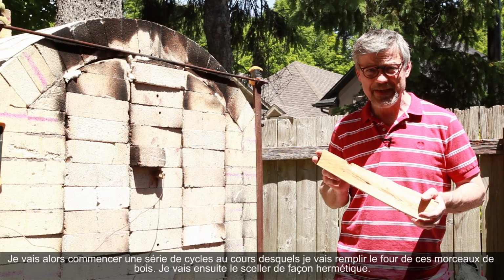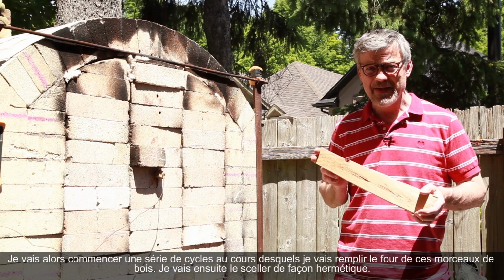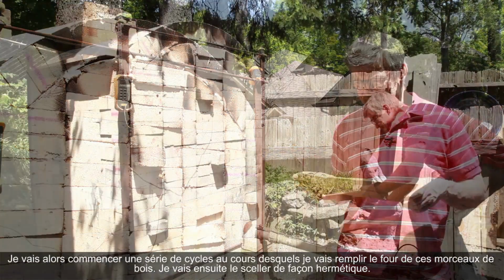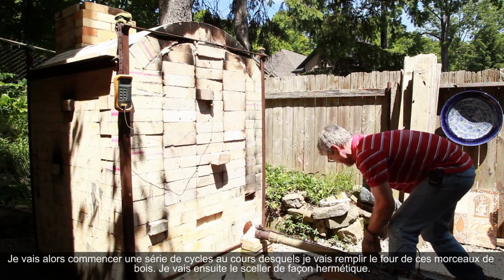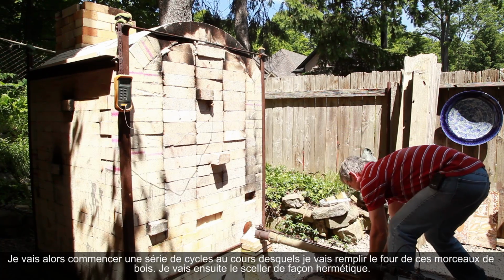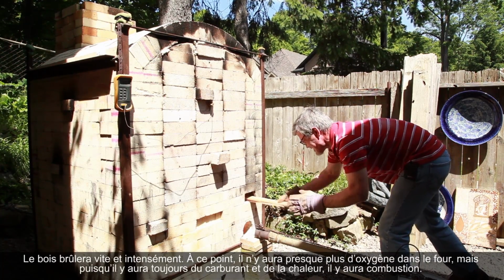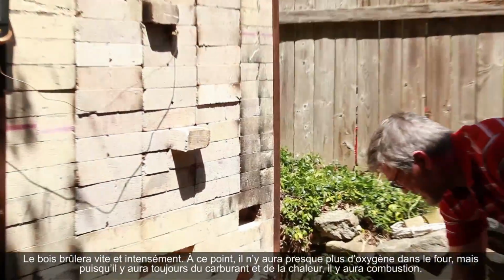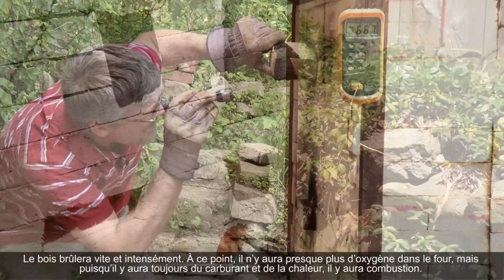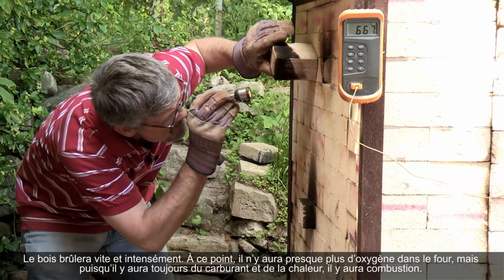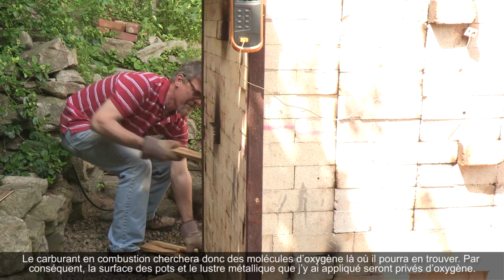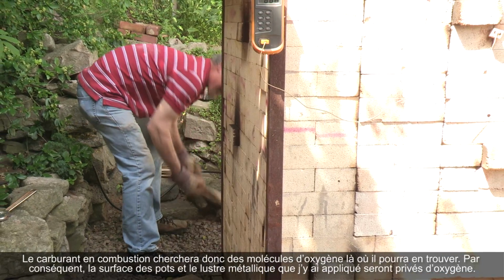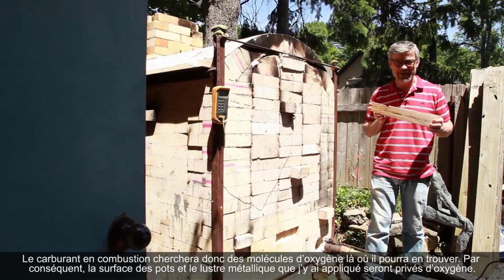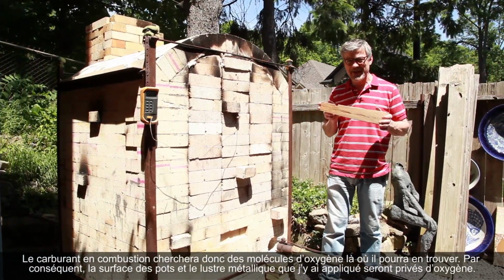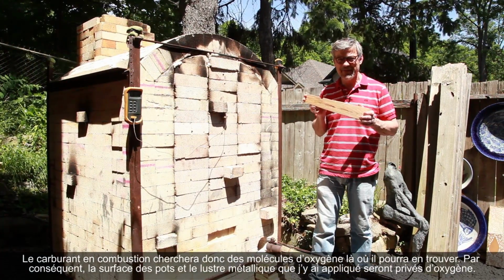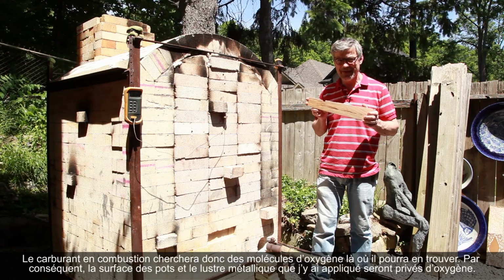And what I'm going to do is several cycles where I charge the kiln or put in these bundles of wood shingles, and seal up the kiln quite tight. And they'll burn really hard, really fast. There will be almost no oxygen going in the kiln, but because there's fuel and because there's heat, there's going to be combustion. And so the burning fuel will be looking for oxygen molecules wherever it can find them. And in this case, it will starve the oxygen from the surface of the pots and from the luster compound that I've decorated on there.